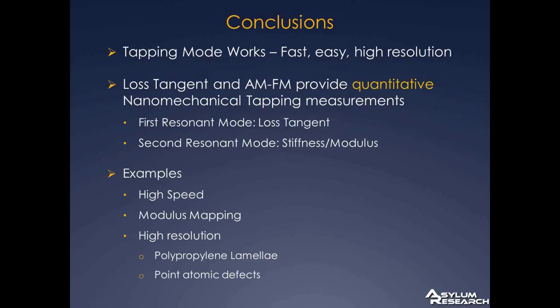I showed you a bunch of examples, hopefully enough, mostly with polymers. We looked at a high-speed image, and there are many more that you can see on our website. Basically, you can image very rough samples and still get modulus measurements or stiffness measurements. I discussed some of the implications and the challenges with modulus mapping, particularly the tip shape. So even though we have